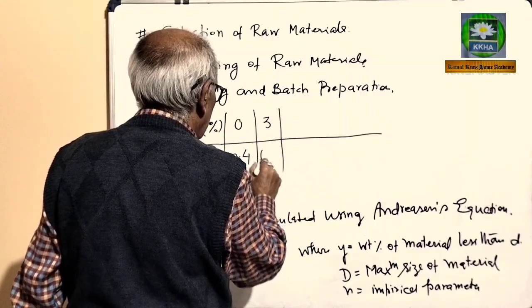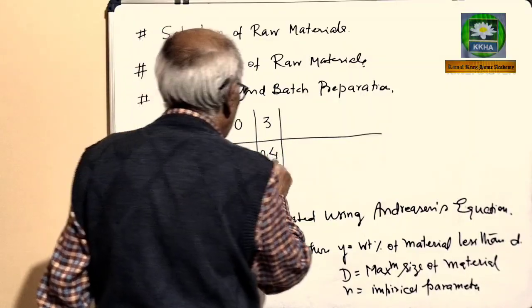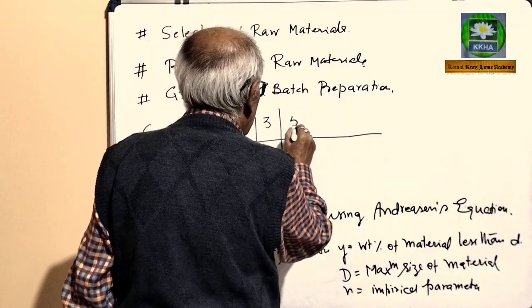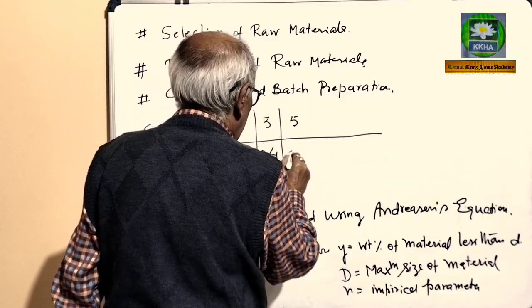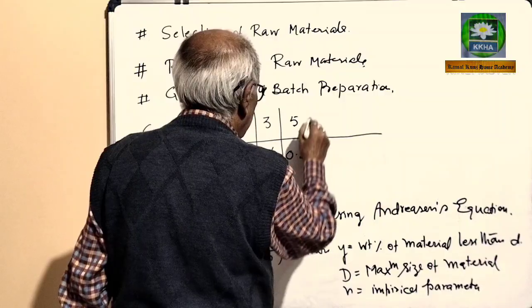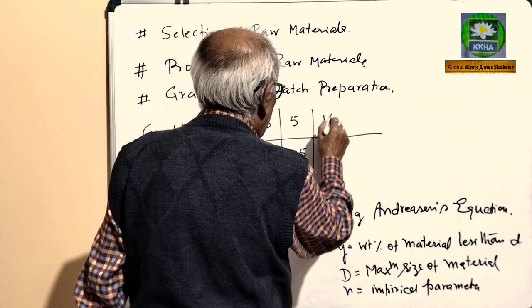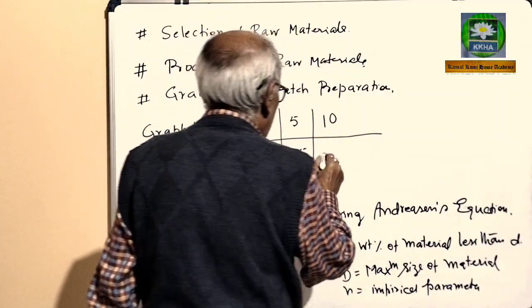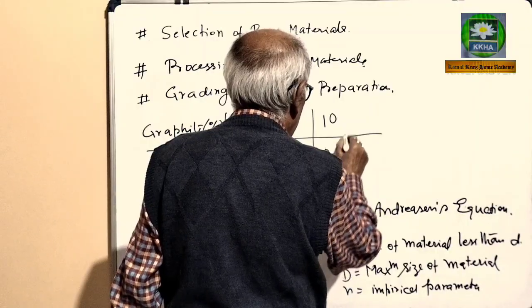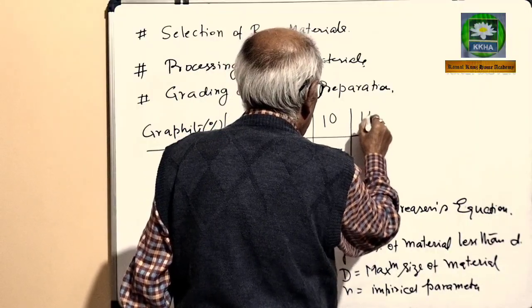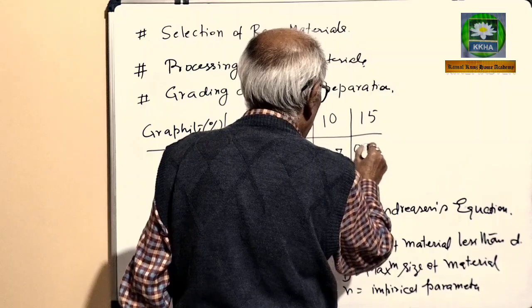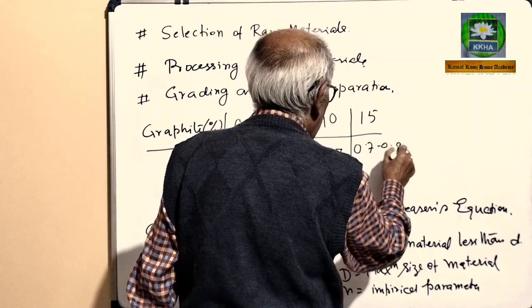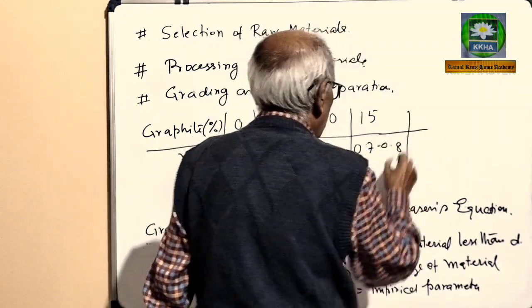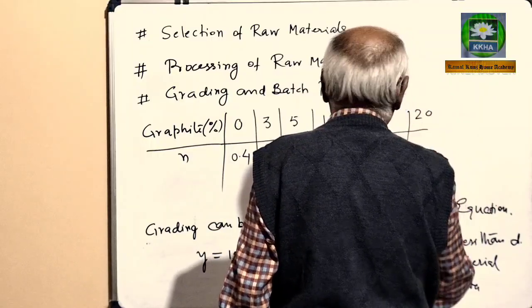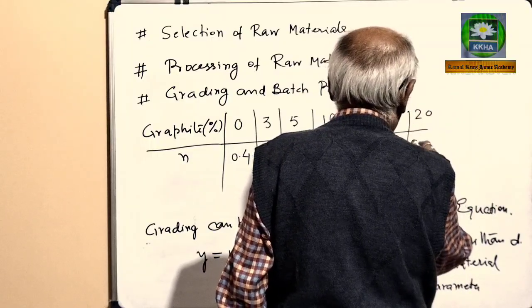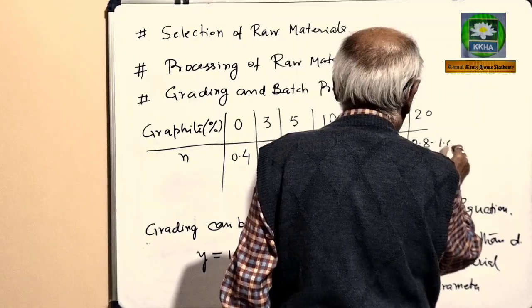At 0%, the value of n is also 0.4. If graphite content is 5%, value of n is 0.5. If graphite is 10%, value of n should be 0.7. If it is 15%, value of n varies between 0.7 and 0.8. If graphite content is 20%, then value of n varies between 0.8 to 1.0.